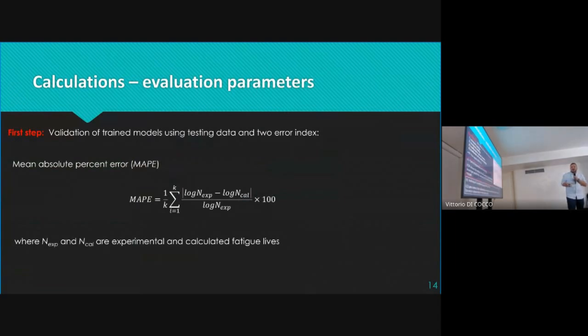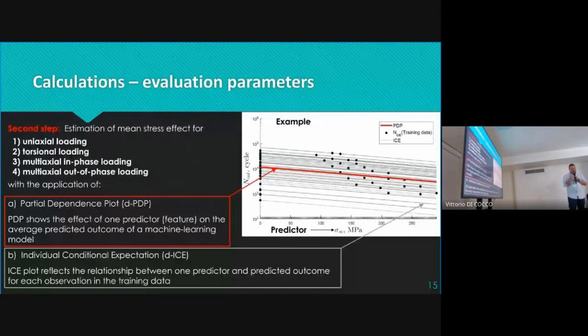So we had 4 groups of materials data sets: uniaxial loadings, torsional loadings, and then multiaxial in-phase loadings and multiaxial out-of-phase loadings. And for each group and each specimen, the ICE parameter was calculated. These are the gray lines. I mean, the dark spots are the actual tested specimens, and within every one of them, we changed the value of the mean stress for this specimen. In this case, the actual mean stress, sigma m, we changed from 0 to the maximum of the mean stress in this data set, in the tests we did, basically. We have to use the model within the boundaries of the data we trained it on. So in this case, it's cut here. I think it was 600 or something like that.